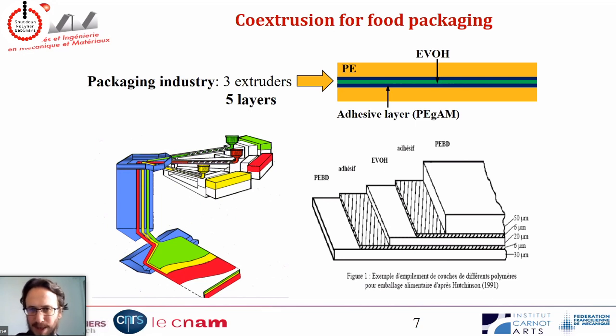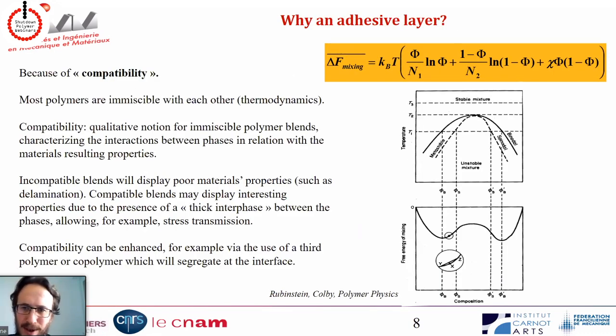So I'm going now to explain a bit more fundamentally what is the role of this tie layer. So this equation on the right is the thermodynamics of mixing. So for 2 polymers, you have this type of equation with an entropic term and an enthalpic one. And this one depends on the Flory interaction parameter. And for polymers, it's usually non-favorable to the mixing, while the entropic term is always favorable to the mixing. But because you have here N1 and N2, which are the degrees of polymerization, which are big numbers for polymers, the entropic term, which favors mixing, is really small. And because the Flory interaction parameter is usually quite high for polymers, then usually the energetic term wins, and the polymers are immiscible, so they don't like each other, you cannot mix them.